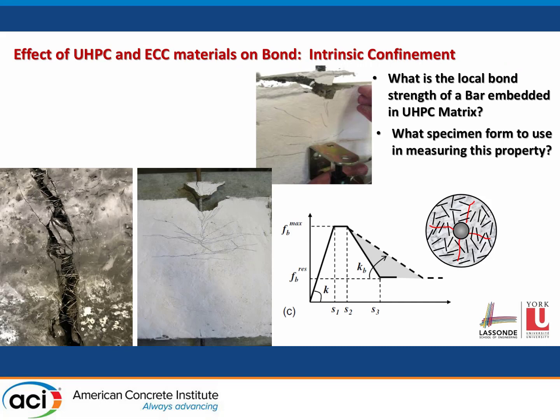So some preliminary tests have shown that when the reinforcement is embedded in UHPC material, you can actually develop very high stresses in the reinforcement, even with a very small cover, on the order of 1 bar diameter cover. You can develop fully the bar capacity without obtaining splitting failures until very large levels of strain develop. The reason for that, we believe, is because the fibers that are intersecting the crack paths provide hoop resistance, which is what you need in order to develop the bar. And this hoop resistance is reflected by an increased amount of fracture energy embedded in the bond slip law, which is shown on the right-hand side at the bottom of the slide by the gray area. That's the increased fracture energy of the reinforcement.